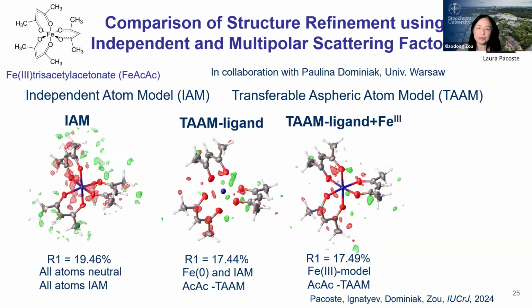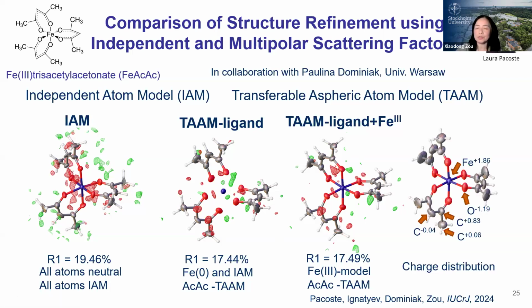From this one, we can see that using the TAAM model, while we still keep the iron neutral, actually we get a quite good, much improved map. And if we model the iron as 3+, the map really doesn't improve very much. That means that it is important to model the ligands to the metal in order to get a much better fit for the map.